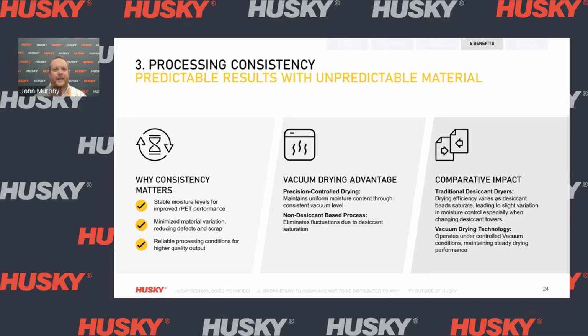The vacuum dryer is able to hold a relatively uniform vacuum pressure level as its means for reducing moisture. In comparison, desiccant-based technology can see small fluctuations in air dew point level as desiccant towers become saturated and when desiccant towers switch from a saturated tower to a dry tower.